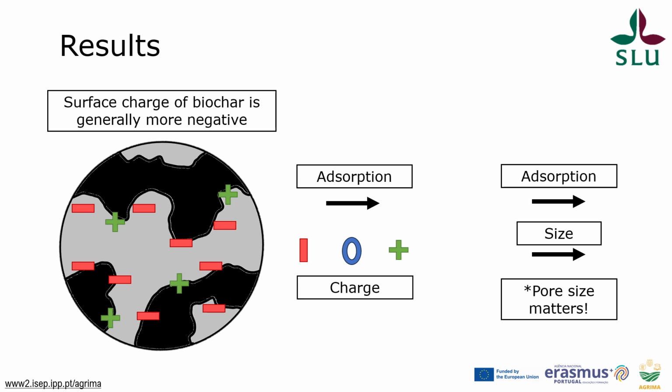However, there's one important thing, is that pore size matters a lot, because the pore size can become too small for these big type of molecules, and then these bigger molecules can't really participate in these pores, and then they basically get pushed through. However, in our case, this was apparently not really the case, and this might be more prevalent for bigger molecules like some antibodies or proteins.